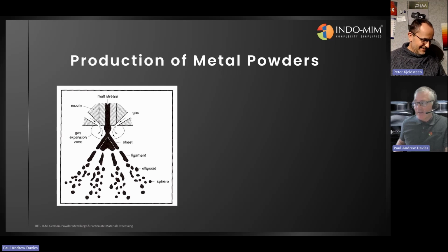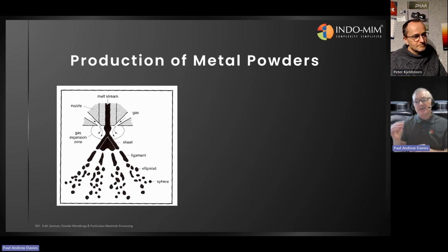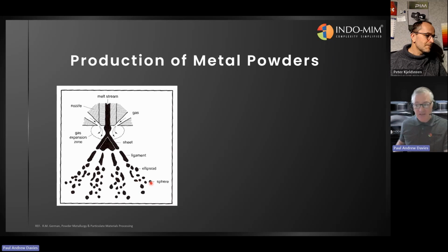Absolutely, and that's really why you have to configure your atomizer, which has a lot of variables. It's the melt temperature of the molten material. It's the metallostatic height above the nozzle. And then the configuration of the atomizer itself, the protrusion of the nozzle, the angles and sizes of the nozzles, and of course the gas temperature, its pressure, and the type of gas all have an influence. Ultimately, the molten material is broken into sheets, ligaments, ellipsoids, sometimes packets of molten material, which then create fine powders, and creating finer powders is probably the biggest challenge.